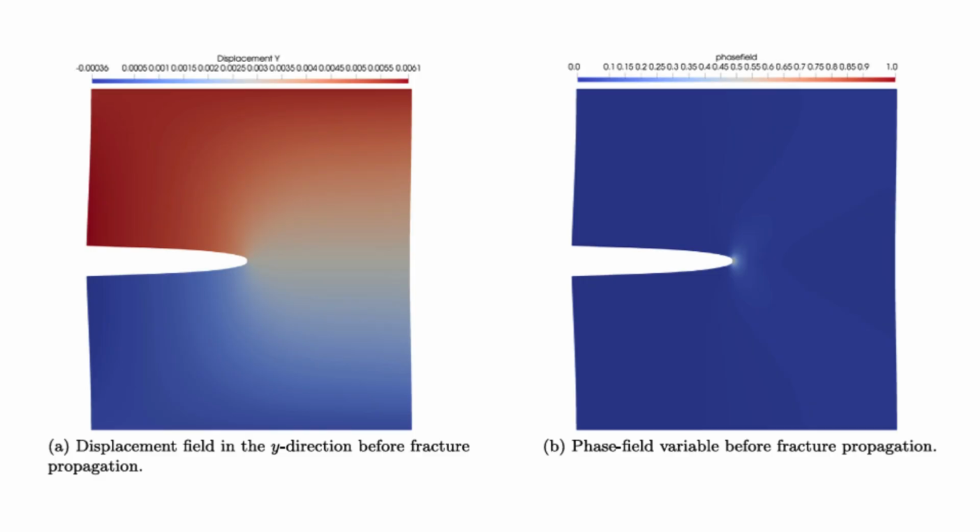Then, the crucial step, the degradation function, the part of the math that lets the damaged material actually grow, they apply it only to the tensile energy part. Ah, so only the pulling energy contributes to making the crack grow. The compression energy is still there, but it doesn't feed the damage. Precisely. It effectively tells the simulation, cracks grow from tension, not from pure compression.